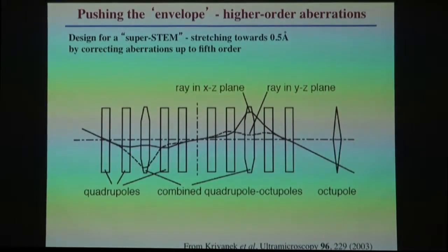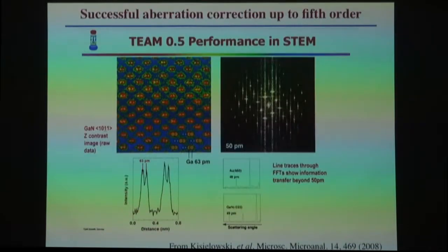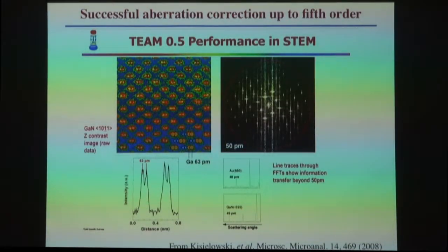Okay, so how do we push the envelope to go to higher and higher resolution? Krivanek proposed to correct the aberrations to fifth order, so how could he get out to half an angstrom? Well, quadrupoles, octopoles, quadrupoles, octopoles, and octopoles. But once you've done it once, it's very easy to start adding more octopoles and quadrupoles. And it was possible to correct aberrations out to the fifth order. And so here is Kisielowski again with the TEAM 0.5 microscope.